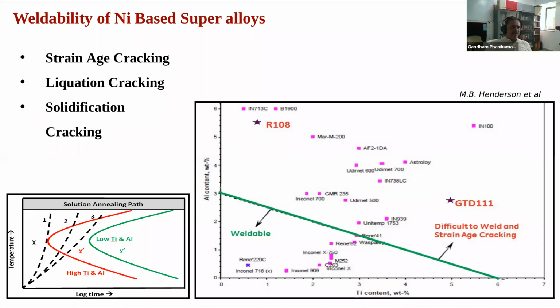So in that context, I want you to note down that there is a map of the titanium and aluminum contents for nickel-based superalloys by Henderson, which actually tells you whether or not an alloy is crackable or weldable, because it has cracking or not. You can see that the domain between the alloy elements is split to show you that certain alloys have inherent cracking possibility and certain alloys are weldable. By weldable, we mean they don't have cracking upon welding. It's the same thing as they don't crack upon printing. So, almost the same.